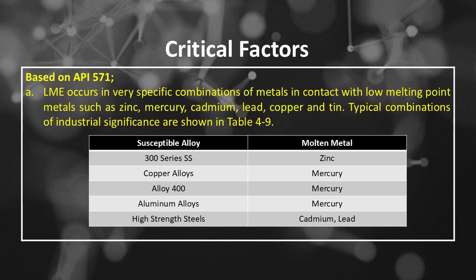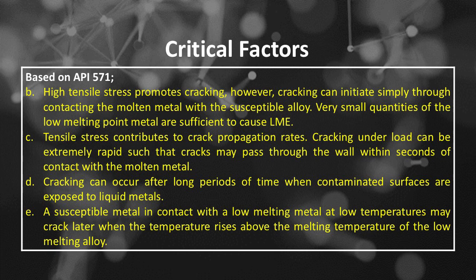Aluminum alloys susceptible to LME when combined with mercury as molten metal, high-strength steel susceptible to LME when combined with cadmium and/or lead as molten metal. Number B, high tensile stress promotes cracking. However, cracking can initiate simply through contacting the molten metal with the susceptible alloy. Very small quantities of the low melting point metal are sufficient to cause LME.